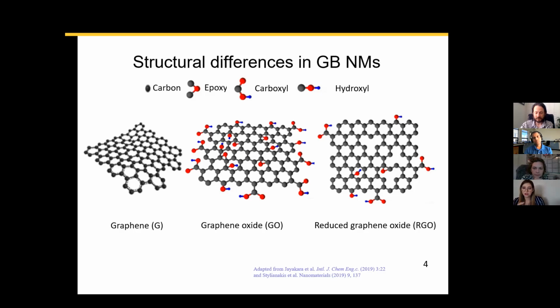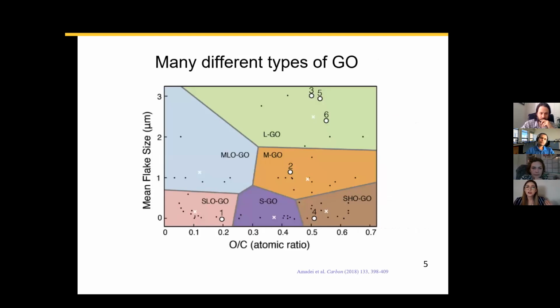We can also tune those oxygen functionalities and create a diverse suite of materials with different functional groups on their structure, ranging from more oxidized to more reduced materials, as we can see in the picture. Now, because of this, we can also see that the graphene materials can have very different properties. And if we look at the literature, we see that a lot of these materials tend to vary in size, but also in oxygen to carbon ratio, which is an indicator of the extent of oxidation that these materials can have. And because of that, they can actually have very different functionalities and applications.